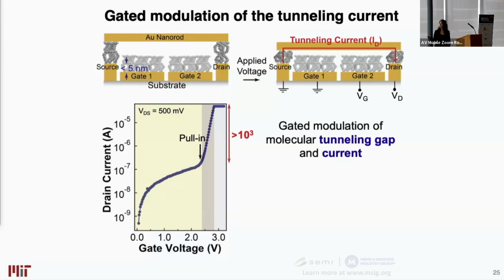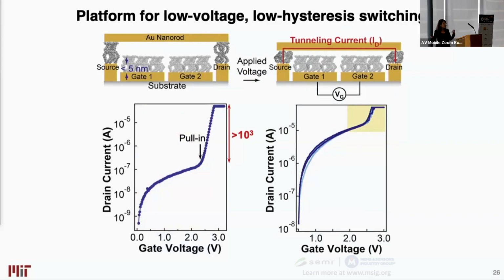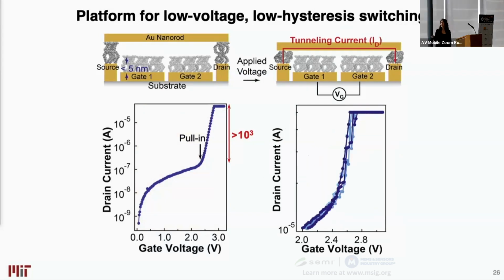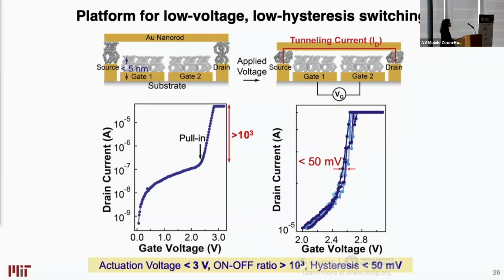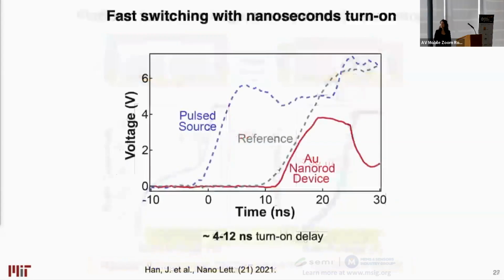So here we're getting more than 3 orders of magnitude modulation of the current. And depending on the structure and the mechanics of the molecule, you can also get very low hysteresis, less than 50 millivolt. So with sub-3 volt actuation voltage, orders of magnitude modulation of the current, as well as potential for sub-50 millivolt hysteresis, this becomes a promising platform to design energy efficient, low stiction electromechanical switches, where you're leveraging quantum tunneling as the main switching mechanism.